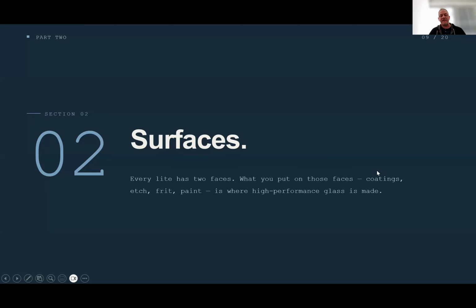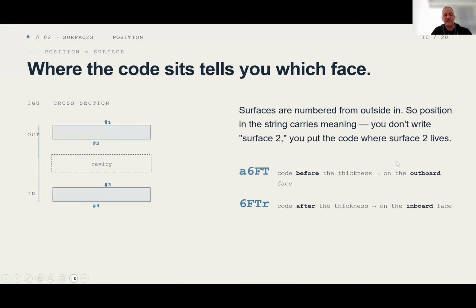So next, as we have the glass, then we can define if something is on a surface. We know we have surface 1, surface 2, we have an inboard, we have an outboard. And so what we've decided was, if the surface code comes before the thickness, it's on the outboard surface. So 1, 3, 5, 7. If it's trailing it, then it's going to be on the inboard surface. So again, it's visual when you're looking at the code. It still gives sort of human feedback on what that looks like, and you can tell visually that this is going to be acid at surface 1 or reflective on surface 4.